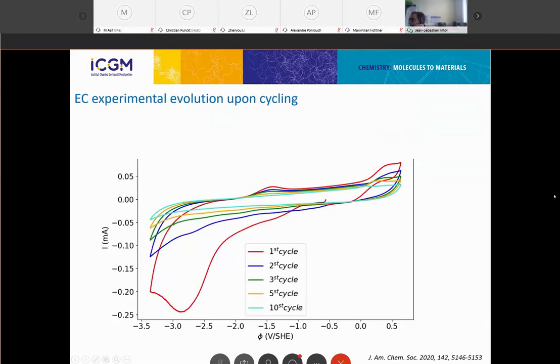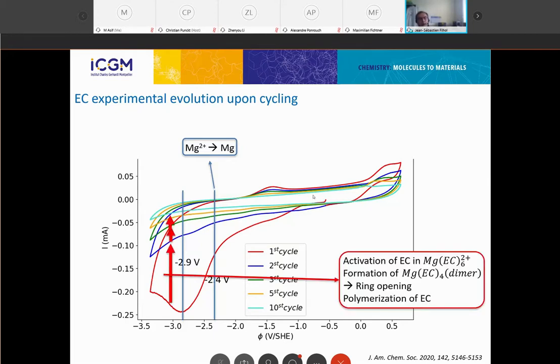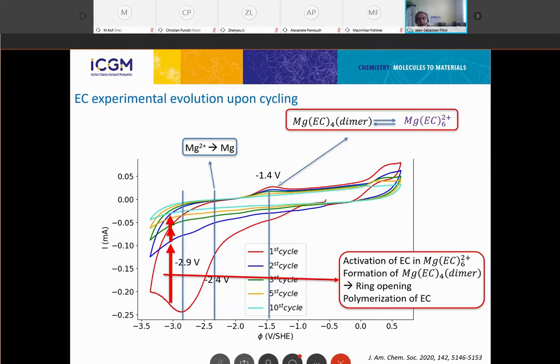In the case of ethylene carbonates, what we observe is, in this case, if I set over there the magnesium 2 plus magnesium reduction process, the potential where the solvent ethylene carbonate is starting to get reduced. We see some kind of decrease in the intensity that probably is linked with the formation of the polymer that starts to form and starts to passivate the whole electrode and decreasing quickly the intensity to very low values. In the second part, what is interesting also with ethylene carbonate is actually we find a peak at around minus 1.4 that directly corresponds to the dimer monomer equilibrium we previously found. So that's certainly one other indirect proof that things are happening with this kind of magnesium.